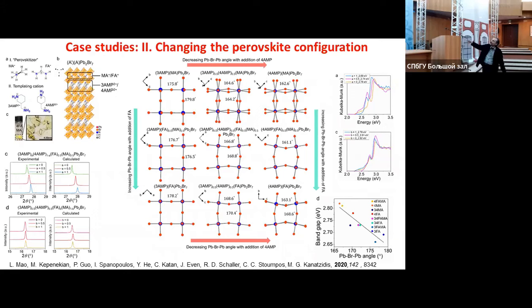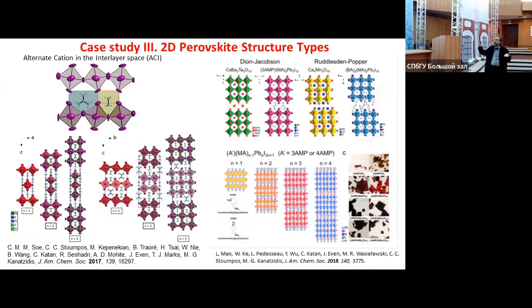This would be the spacer, and playing with the two perovskitizers, methylammonium and formamidinium. You are able to adjust the properties within the bilayer, because all these have been tried for a bilayer perovskite. So there is a lot of chemistry here that we can do and fine-tune a little bit the excitonic properties from undistorted to distorted. But there is a lot of work that can be done here, and that's my favorite part.